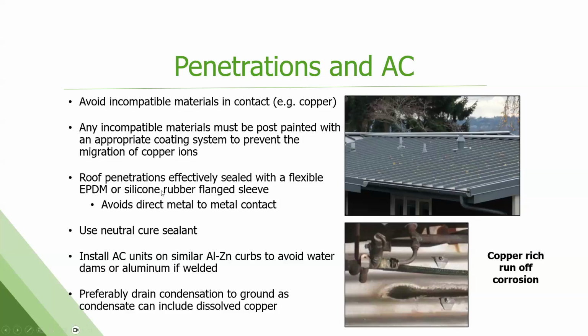Again, got to seal roof penetrations. Make sure you're not getting water up underneath the panels. It'll corrode from the backside out. Use a neutral cure sealant. And install AC units on similar material curbs. So you can do your curbs with the same Galvalume product that the roof panels are made out of. So then you don't have an incompatibility.